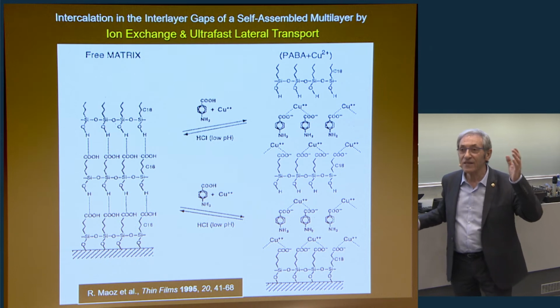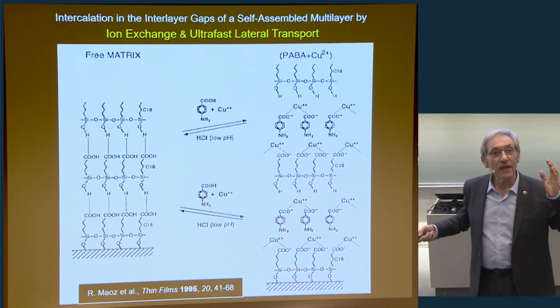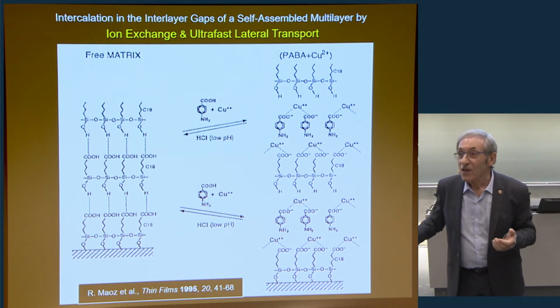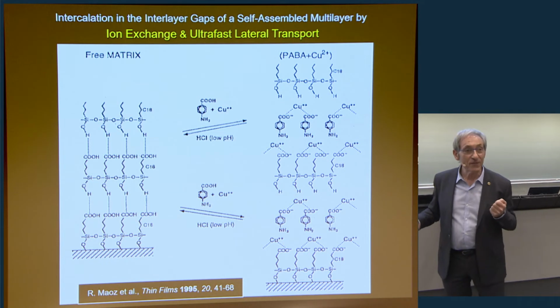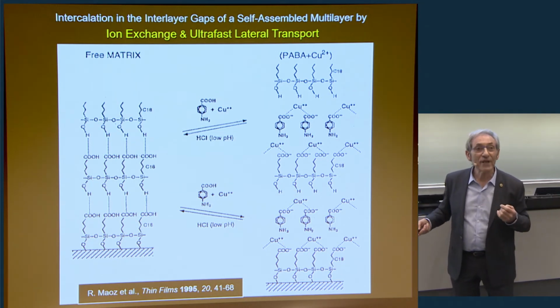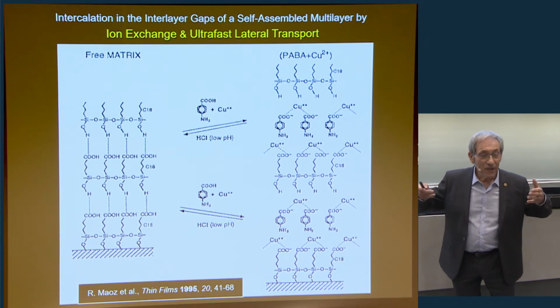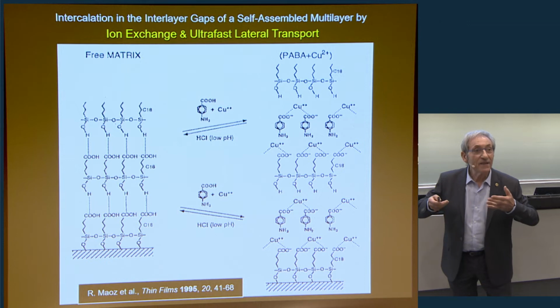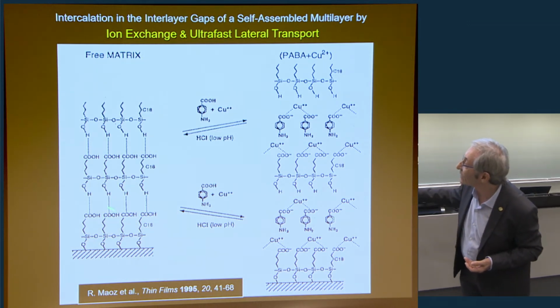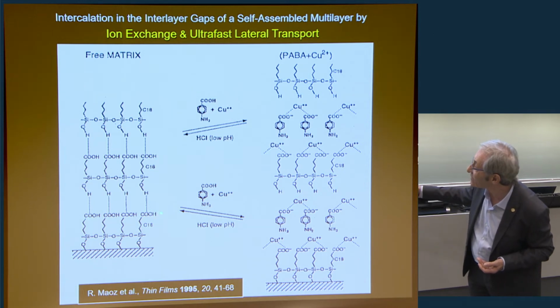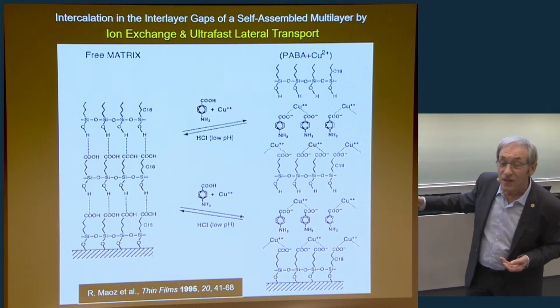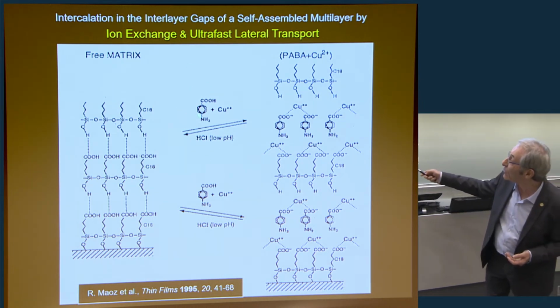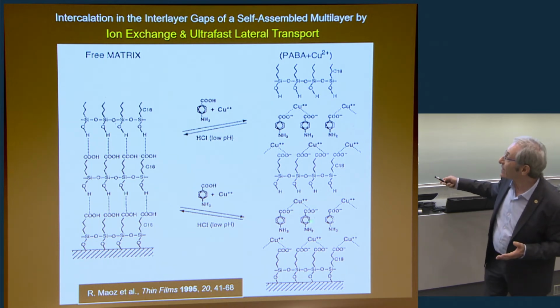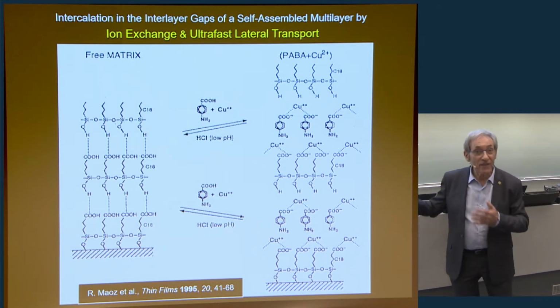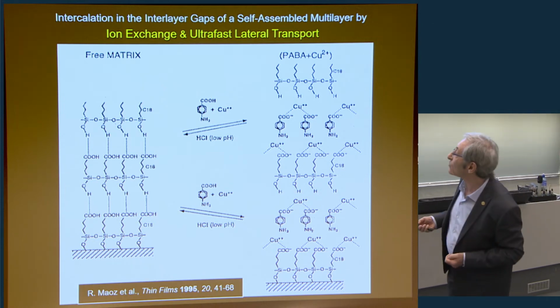At that time, there was high interest in making structures that exhibit the phenomenon of second harmonic generation. For second harmonic generation, we need a non-centrosymmetric structure. With Langmuir-Blodgett, you always obtain centrosymmetric structures, I mean, the polar interfaces are centrosymmetric. Here, inherently, we have non-centrosymmetric. Here we have a layer of carboxylic acid groups, and we have a layer of silanol groups. So this forces this molecule, which is a polar molecule, to orient itself automatically with the amine toward the carboxylic acid and with the carboxylate toward the silanol. So this indeed exhibited the property that we expected.